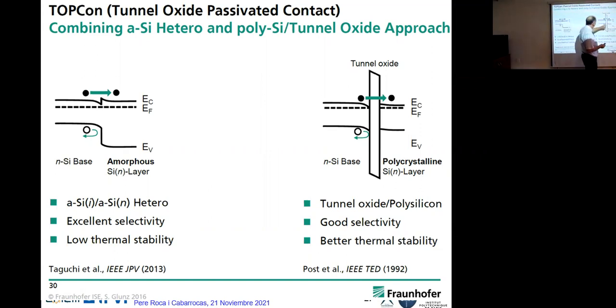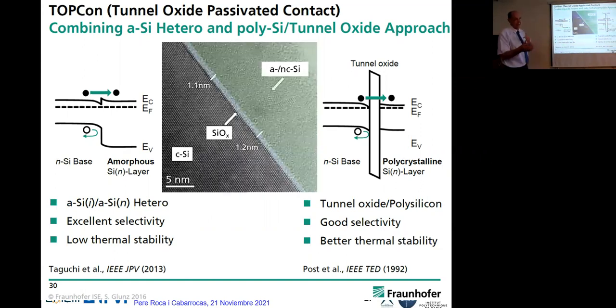Now the game is: I can have surface passivation, but I want electrons going through. So you have to be able to control a very thin oxide layer to have a tunnel effect. It has taken again 20 years to optimize this 1.2 nanometer silicon oxide layer, which provides the passivation, and then you have polysilicon, P++ or N++ contact, to act as a selective contact for electrons or holes. So that's what is coming up.